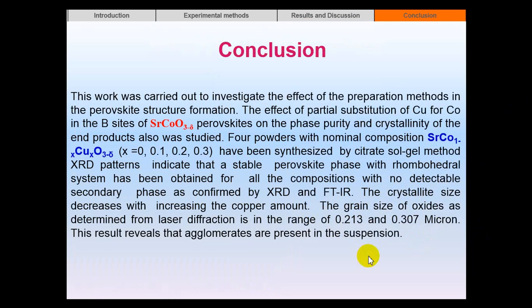Now, conclusion. This work was carried out to investigate the effects of the preparation method on the perovskite structure formation. The effects of partial substitution of Cu for cobalt in the B site of SrCoO3-δ perovskites on the phase purity and crystallinity of the end products were also studied. Powders with nominal composition SrCo1-xCuxO3-δ have been synthesized by the sol-gel method. XRD patterns indicate that a stable perovskite phase with rhombohedral system has been obtained for all the compositions with no detectable secondary phase, as confirmed by XRD and FTIR.